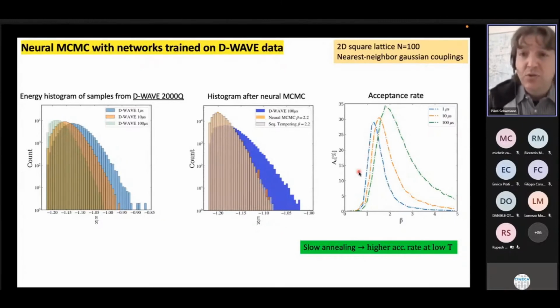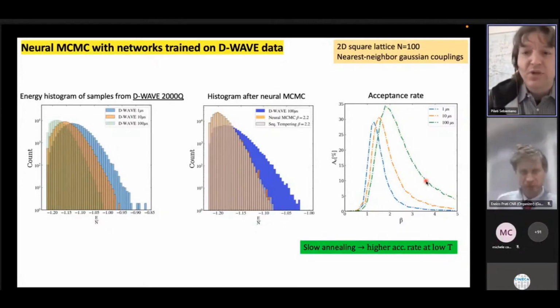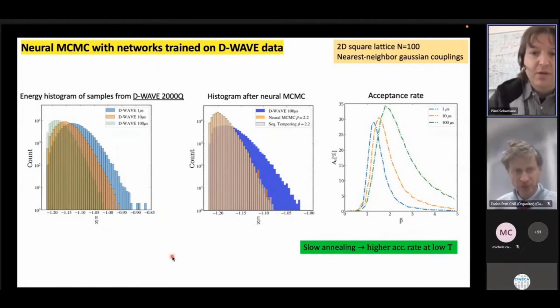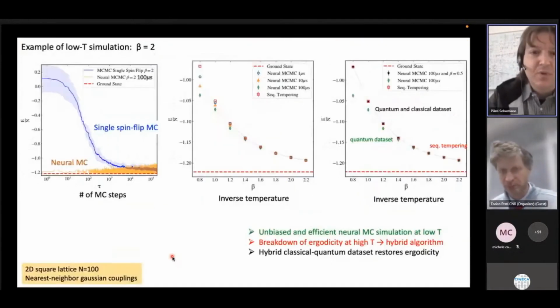And what is interesting to notice is that the acceptance rate becomes higher, in particular at low temperature, so for large beta, okay, if your neural network has been trained on the D-Wave data obtained with a longer annealing time, okay, because that's where you expect to explore more frequently the low energy part of the configuration space.